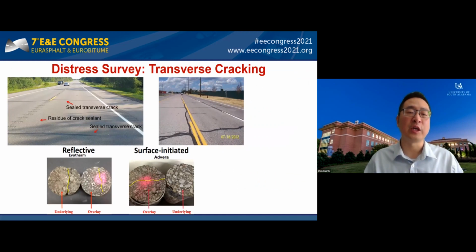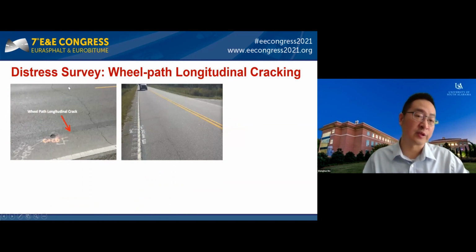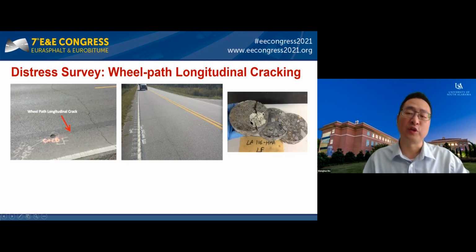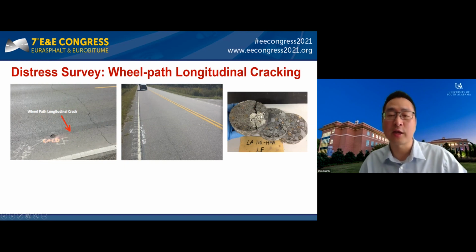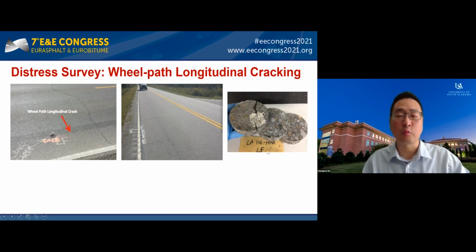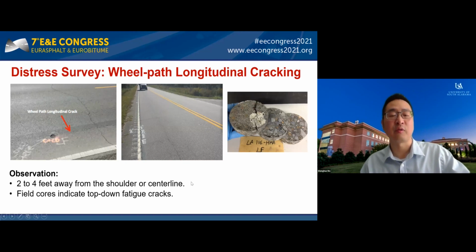I want to discuss the major distresses, in terms of the transverse cracking. As we can see, for transverse cracking, we also find that there are both reflection cracking and surface-initiated cracking. So this is indicating that the transverse cracking is not only thermal cracking related, but also maybe a reflection. Another major type of distress we find is the wheel path longitudinal cracking. So we also take the field core at the tip of the crack. We slice the core into different layers, and we can see that the crack starts from the top and propagates downward. So this is indicating that the wheel path longitudinal cracks are all top-down fatigue cracks.